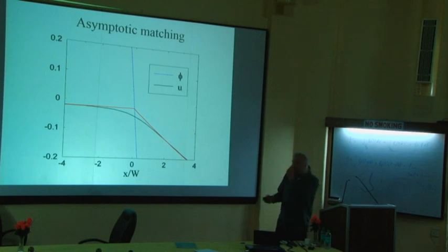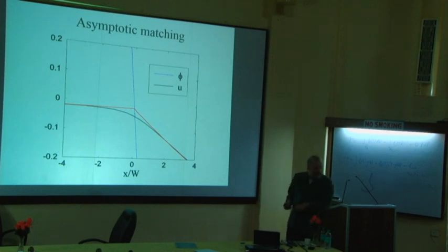Okay? So this value of the crossing of the red line with the interface position, this is the effective boundary condition that is imposed on the outer field by the phase field. And you can see that this boundary condition actually depends on the structure of the temperature field inside the phase field, inside the interface. So it's a non-trivial calculation. You have to solve this inner problem, and you have to calculate the entire solution for this temperature field in order to get the right boundary conditions.